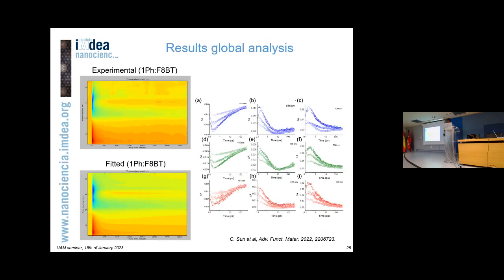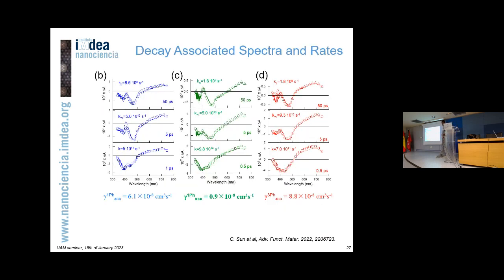These are basically the results. This is the experimental matrix, and this is the reconstructed matrix. What does this mean? Essentially, we obtain decay associated spectra for the different contributions: singlets in the host polymer, singlets in F8BT, and substructure states. But the main point is that we obtain the rates for the different species and also the annihilation rate.